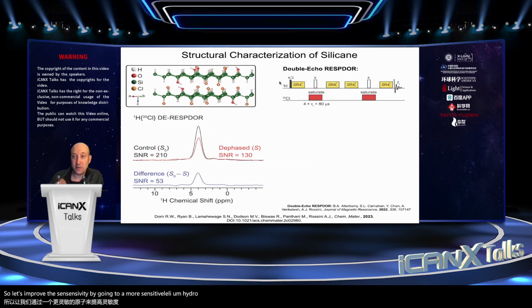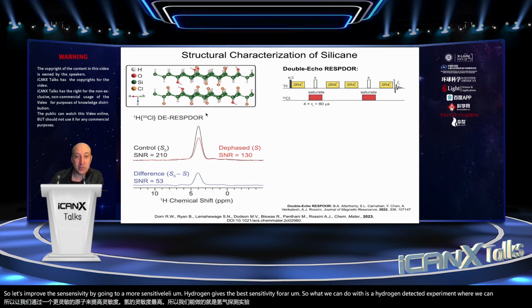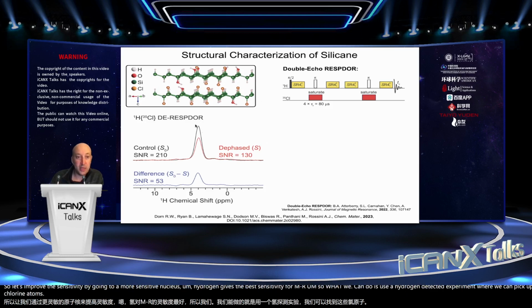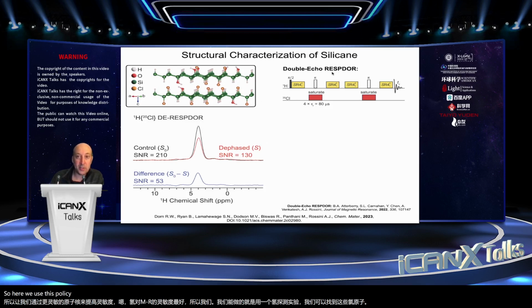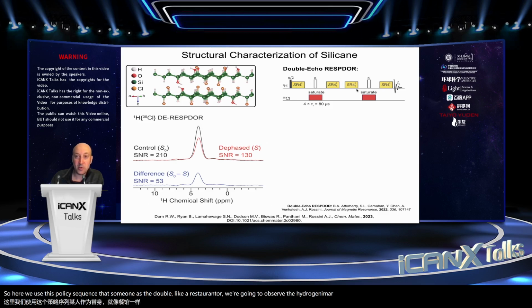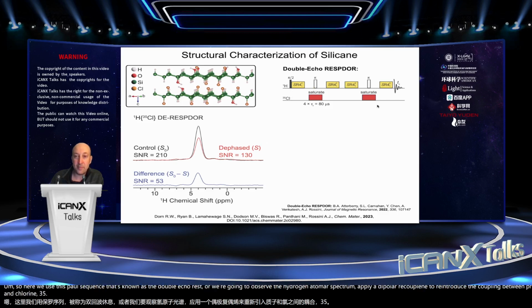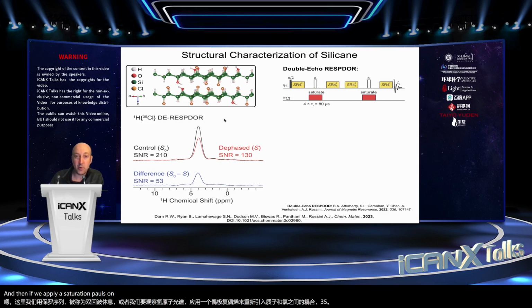Hydrogen gives the best sensitivity for NMR. So what we can do is a hydrogen-detected experiment where we can pick up these chlorine atoms. Here we use this pulse sequence that's known as Double-Echo RESPDOR. We're going to observe the hydrogen NMR spectrum, apply dipolar recoupling to reintroduce the couplings between proton and chlorine-35. And then if we apply a saturation pulse on the chlorine spins, we'll see a reduction in signal if our hydrogen atoms are within a couple angstroms of a chlorine.